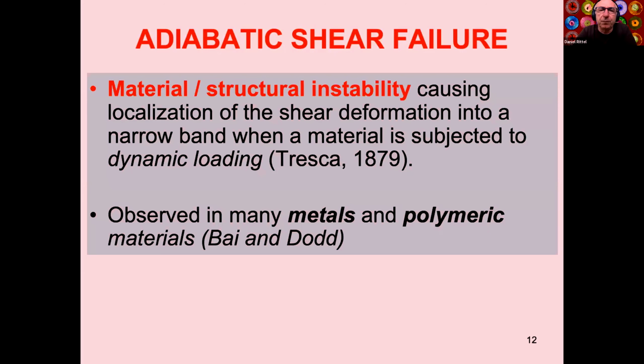Well, it's a material or structural instability in which homogeneous deformation all of a sudden becomes heterogeneous, localized into shear deformation. And you get what people call an adiabatic shear band, or a narrow band, which in fact is a plane. It's not a band, it's not two-dimensional. But when you perform metallurgical sections, it looks two-dimensional.